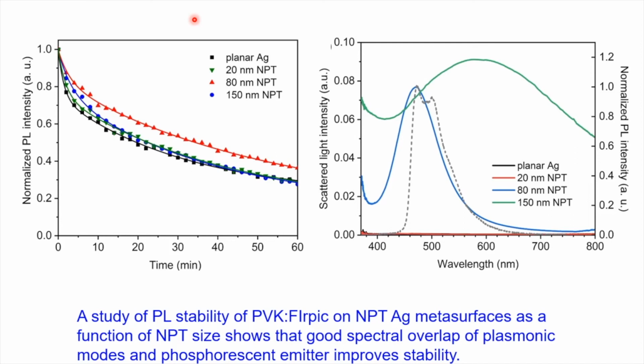So again, this is further proof that the localized surface plasmon resonances of the metasurfaces are responsible for the improvement in the stability of the phosphor on these surfaces. Taking a look at planar silver and then three different nanoparticle sizes on the metasurface, for 20 nanometer diameter nanoparticles, as well as 150 nanometer diameter particles, there isn't a significant improvement in the stability. However, at the 80 nanometer size, the intermediate one is actually the best, and that's the one that was used in the aforementioned results as well.